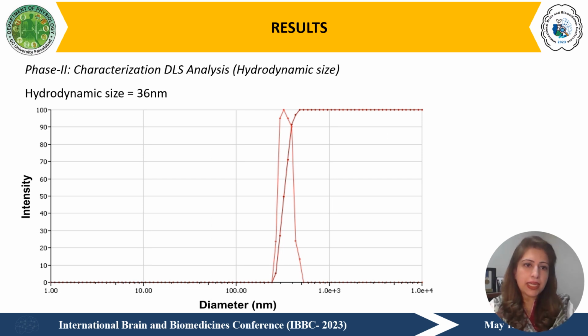The dynamic light scattering analysis was carried out for the hydrodynamic size, and the hydrodynamic size of these titanium oxide nanoparticles calculated by the DLS was about 36 nanometer.